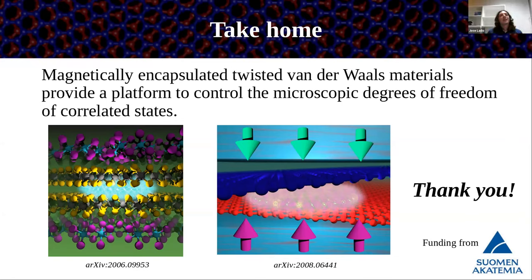Yes, that's of course a very interesting point. So in the case of graphene, one can easily estimate at which angle one gets the magic angle. That is essentially a ratio between the distance in momentum space between your Dirac points and your interlayer coupling. And those are two energy scales or two wavelength scales that you can easily estimate. If you just say, oh, my interlayer coupling is 300 meV, for which angle would I get a splitting that exactly gives me flat bands. So for twisted bilayer graphene, it's fairly easy.